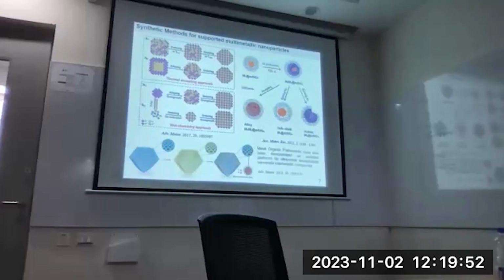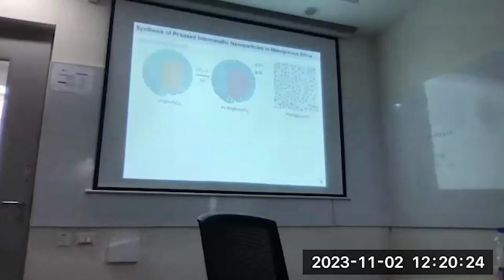Right? So we also use metal organic frameworks, but these are expensive because of the yield of your metal organic framework, and sometimes you're using zirconium. Most of the metal organic frameworks these days use zirconium, and some of them use aluminum and other compounds. But these are very good at controlling your size. You can get very small nanoclusters of these metals. So basically, you have a very highly dispersed catalyst, and you have these pores for the liquids and the gases to interact very easily. Right? So we can use these also as supports, and then silica, conventionally, silica also is good.